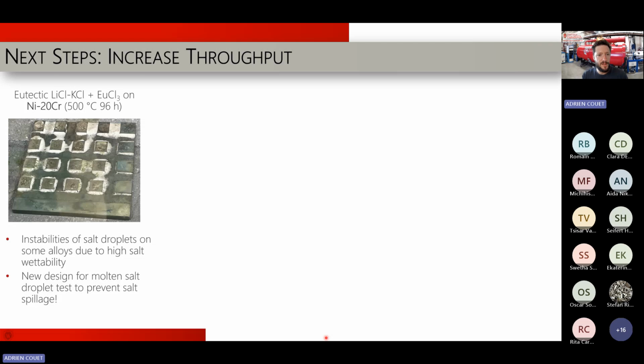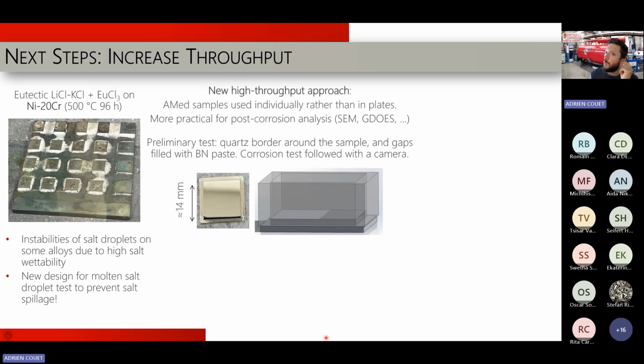The truth is not all the tests are very successful. We have also tests that fail terribly when the droplet basically just spills and disappears. And that happens a lot when we're working on nickel-rich elements, especially nickel binary chrome. And we think that's because it's very wettable. There is a good wettability, and then the droplet spills like that. So we want to make a more robust corrosion test for these high-throughput experiments.